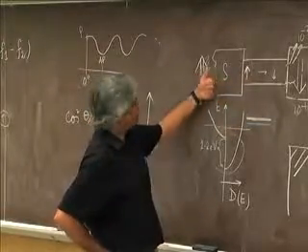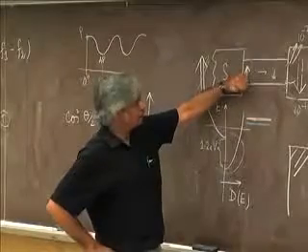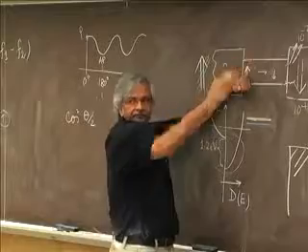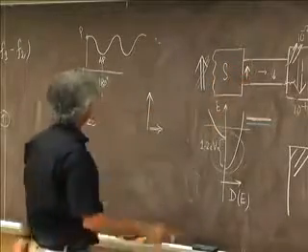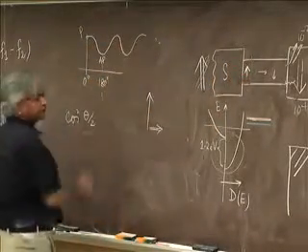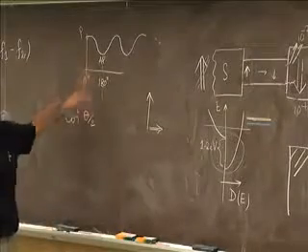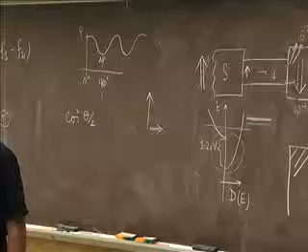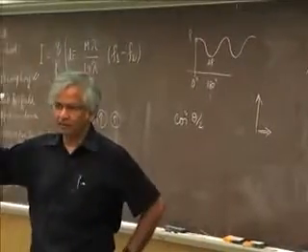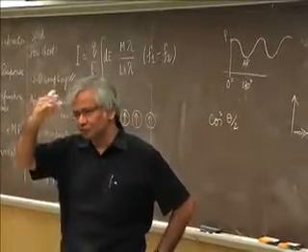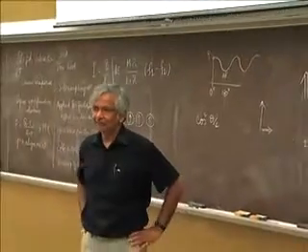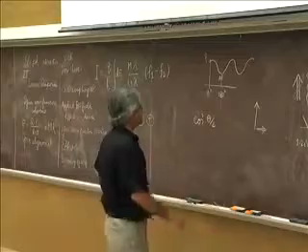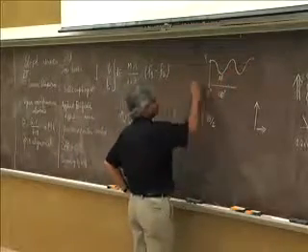So it's like, okay, I inject spins this way, and I put a magnetic field this way, let's say. Then what will happen is it will precess. And the current should be oscillating like this. Now, usually, I think there are experiments by Appelbaum which show many, many oscillations, like maybe 5 or 10 periods. But most of them usually just show barely one oscillation or so, because after that, usually, again, coherence issues come in. So you don't quite see this clean theorist's curve like this.